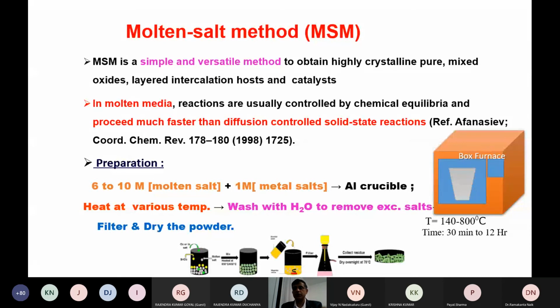The beauty of this technique is that depending on the materials, temperature and time can also be varied. And you don't need any surfactant or any expensive things. With a simple alumina crucible and a beaker, you can prepare the material. In this way, if people want to do an MTech or any students, I think this method is a little bit simple, and you can do the project, and at least you can get 5 to 10 grams of the sample.